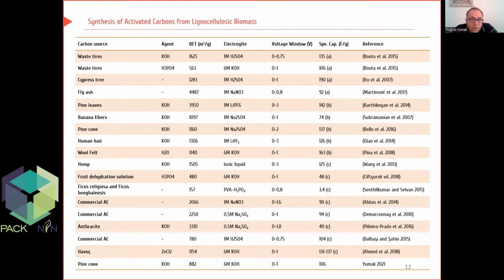As you see, the activated carbon obtained by KOH activation from pine leaves has an extreme surface area of almost 4,000 square meters per gram, and the specific capacitance is almost 140 farads per gram.